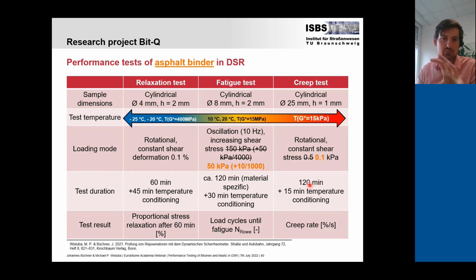I have not prepared any results of the binder, because it's just very recent that we also included the binder testing. But what the results show is that it might be enough to check only the asphalt binder. The filler does not have such a big influence when you look at good fillers. So in our case, we had very much experience with all the fillers. These are empirical experiences that these fillers will work also very well in practice on site. So this is still work in progress. There are already some publications, but we are still working on that.